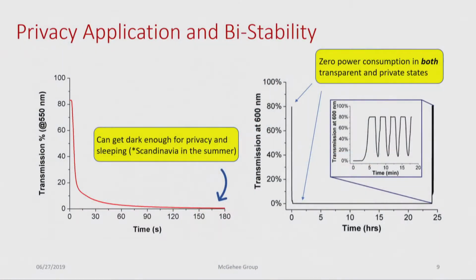One thing I wanted to mention as well is that there are some additional benefits to using metals for electrochromic applications. Specifically, we have a much wider optical range that we can work with compared to other technologies for electrochromics. What I mean by that is that if we just keep plating more and more metal on the TCO surface, the window will continue to get darker and darker. Specifically, we're able, within 3 minutes, to get below 0.1% transmission, which is usually the numerical value associated with trying to reach privacy applications. So we could have potential applications in residential markets.